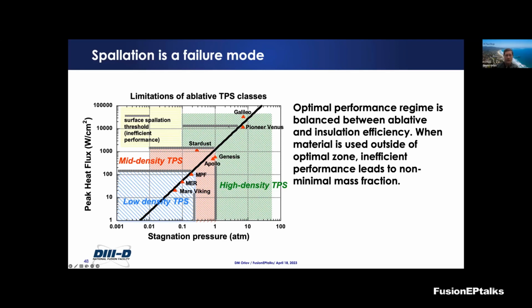This is not the way the material should behave. We should probably try to stay away from or delay this zone as much as possible, because that would typically lead to very different aerodynamic characteristics, leading to loss of the ablative material that won't be used for ablative heat flux reduction.